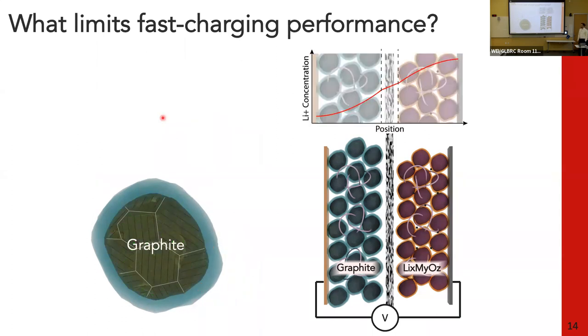All right. But when I want a fast charge, so this is kind of the starting point for fast charging, if I want a fast charge, I have these lithium ions that are hanging out in the liquid electrolyte, and I start driving current across this electrolyte really fast. What happens is you get a concentration gradient through the thickness and across the cell. So the concentration of lithium ions at the electrolyte separator interface is higher than deep within the graphite electrode.